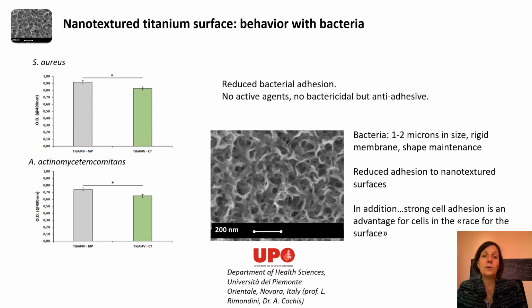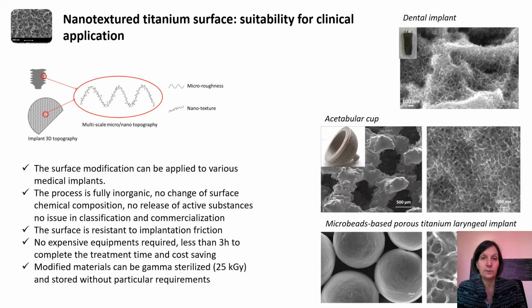And it is also of interest that on this surface we have a reduced bacterial adhesion, so we have a passive action against bacteria. We have no active antibacterial agent on the surface, but because of the topography and the chemistry, we are able to reduce the adhesion of different bacteria. And further development is the functionalization with an active antibacterial compound.